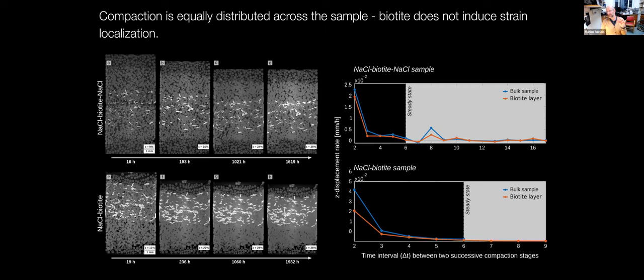Otherwise, there's no localization. It would have to compact more. The fact that this did not happen is shown here. This is just a shortening of the biotite layer plotted against the entire sample. And the hypothesis was if there's strain localization, the biotite layer must compact more than the rest in percent, right? And it didn't. Compaction is uniformly distributed throughout the sample.